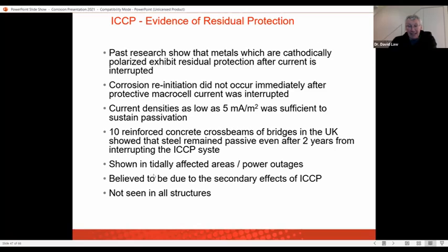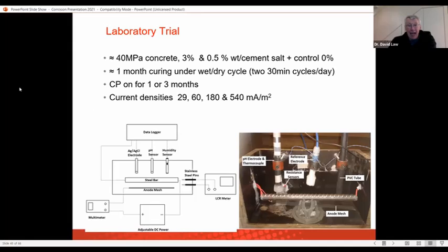However, what we've seen is that this is not seen in all structures. And in particular, it's sometimes affected in tidal areas. So we need to understand what these factors are. And to do this, we've set up dual trials. We set up some laboratory trials where we cast specimens, and here we would have a steel bar and an anode mesh, and we would monitor pH, potential, and humidity within these to see how long they would give residual protection for.